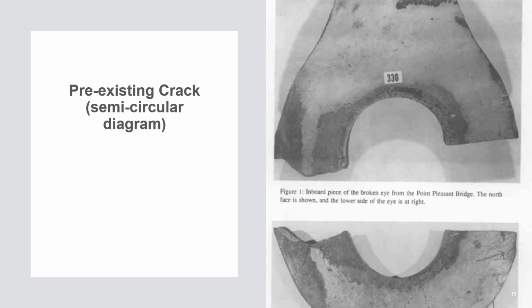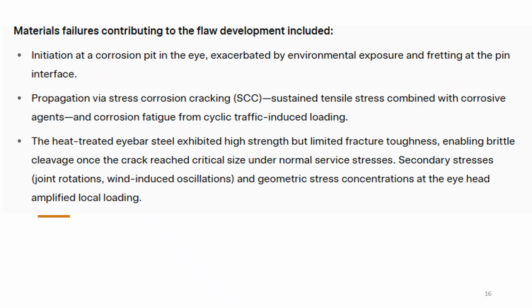This flaw grew slowly over the bridge's 40-year life through the synergistic mechanisms of stress corrosion cracking, where sustained tensile stress and mild atmospheric corrosives, including moisture and possible sulfur compounds, promoted intergranular crack advancement, and corrosion fatigue, in which cyclic loading from vehicles accelerated propagation along the crack front. The material's microstructure, high hardness from heat treatment, offered low fracture toughness, allowing a sudden cleavage brittle fracture once the crack reached critical size under normal service conditions. The single failure severed the non-redundant chain, triggering catastrophic progressive collapse.